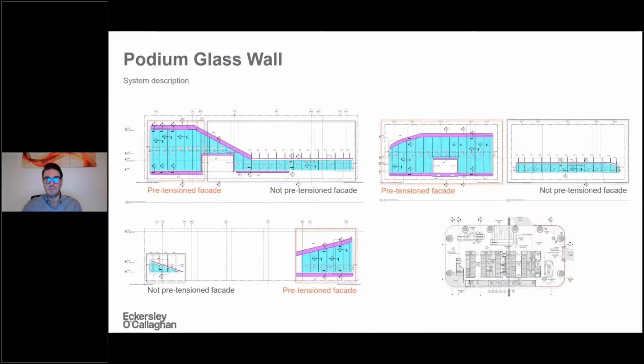For the system description, the facade was wrapping around all four sides of the podium, but clearly with varying height, and therefore not all the areas needed a pre-stressed cable. So in these four elevations of the podium, we show where the pretension facades are. In this area the glass is up to 15 meters tall, while in all the other areas the glass goes up to 4 meters, and the system was a simply supported beam spanning from top to bottom.